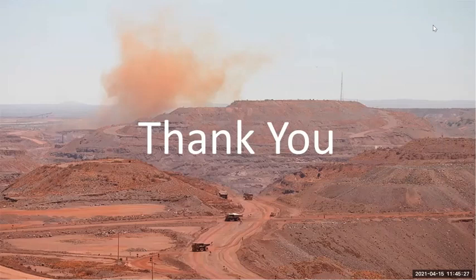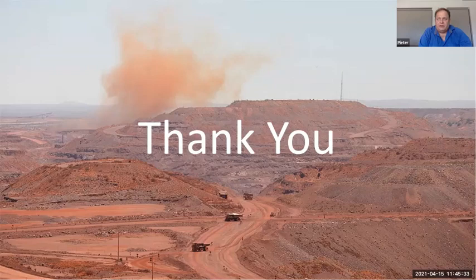Yeah, I'll take that question. Stockpile sampling is definitely a big challenge. As we know, with stockpiles you get segregation, you get variabilities in the ore. If you go through the ISO standards, there's a process using a sample auger when you have fine material, but for large stockpiles, let's say run of mine, unfortunately you have to go back to the tried and tested method of opening the stockpile with a front-end loader, making sure you have access to the bottom part and the deeper side of the stockpile. You need to take more samples than prescribed by the ISO standards to cater for the variability of the stockpile. You need to take samples bottom, top, and middle to address segregation.